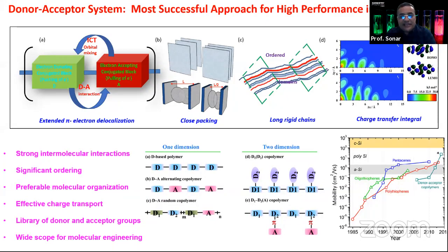And as the pi-pi stacking distance gets reduced, since the semi-crystalline nature of this polymer backbone is enhanced, the charge carrier mobility gets very high. Because of this crystalline domain, the charge can easily hop upon the electrical bias. And by putting this donor-acceptor combination, we can really make a strong donor strong acceptor, or weak donor weak acceptor, or strong donor weak acceptor. With this permutation and combination, we can really make a lot of interesting